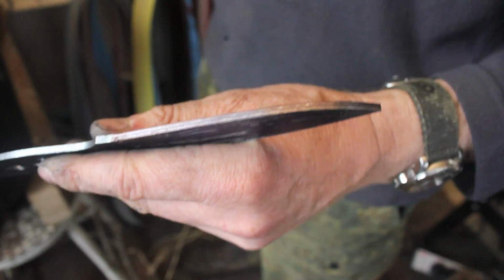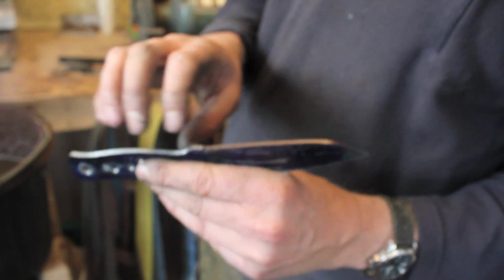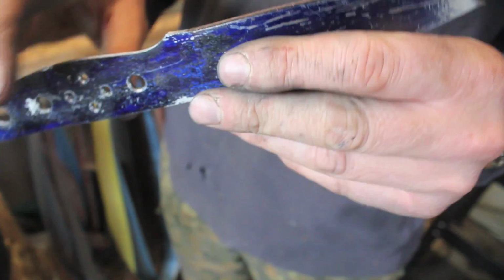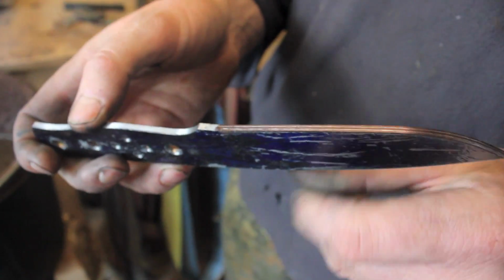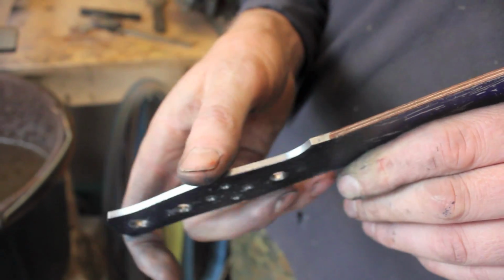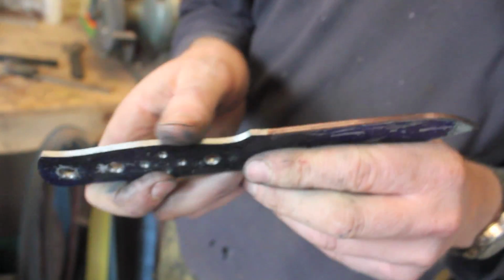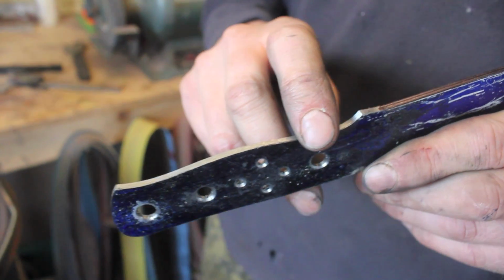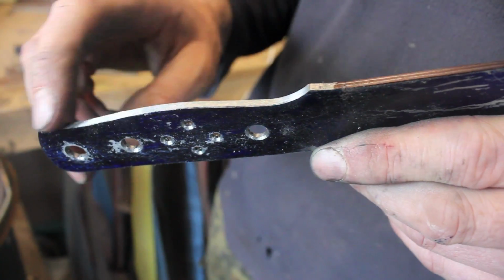That gives me a bit of steel to take down after heat treat, because during the heat treat process you get this thing called decarburization. Now I do things in my kiln to minimise that, which you'll see later. Trade secret, trade secret. I'll censor that out. But obviously I don't want to remove too much carbon from the steel.